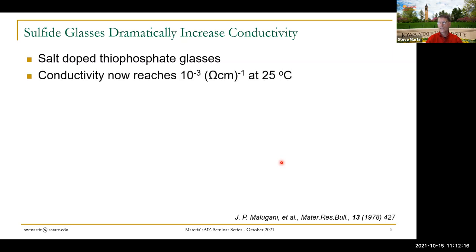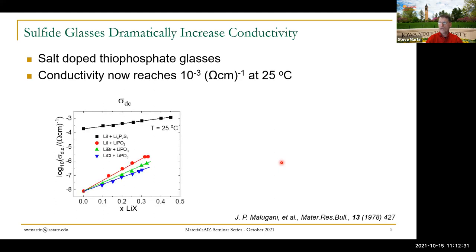So Pierre and Beege and other people in this community have been listening to me talk about these sulfide glasses, one step down the periodic table. And then you can dope them with salt, just like you dope sodium chloride into water and increase the conductivity. And now you reach a value about 10 to the minus three. Orders of magnitude, of course, lower than the electronic metallic conductivity of 10 to the seven and 10 to the eight. But nonetheless, this 10 to the minus three conductivity at room temperature is pretty much a known benchmark